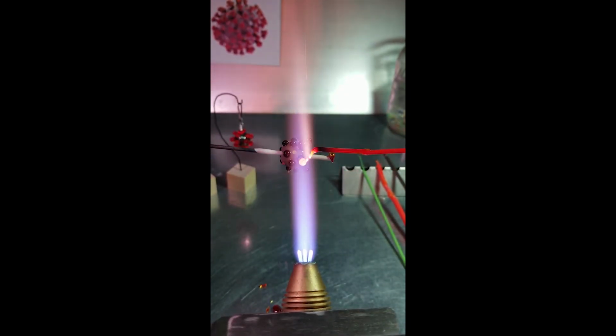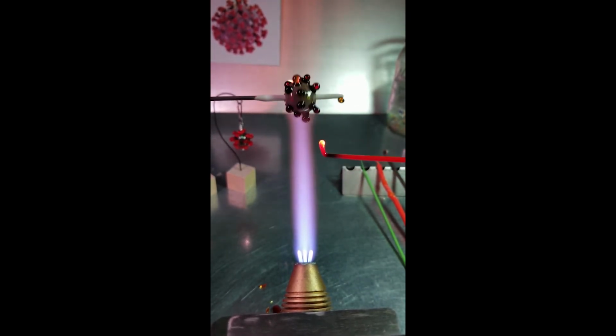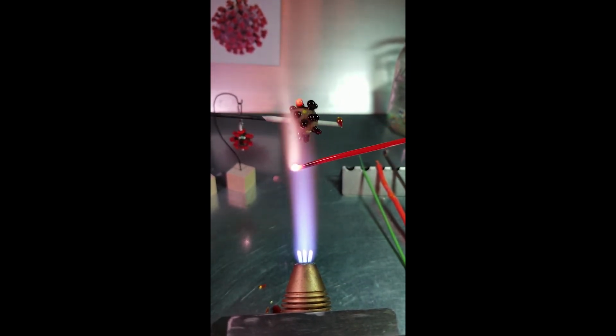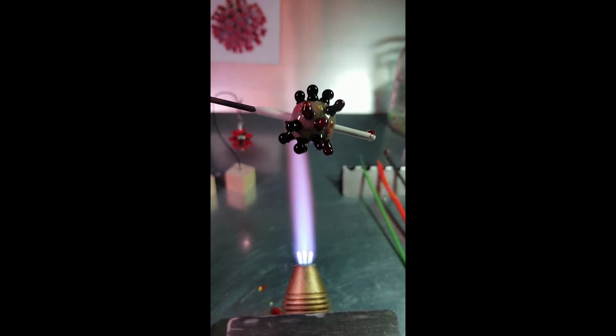Now I'm just going through, speeding it up again. I'm adding all of those balls on top, making sure they're all about the same size. I'm also keeping my base bead warm, because if I let the base bead cool down while I'm adding all these details, that can thermal shock and crack. So I do need to make sure I waft it through the flame and keep the base bead warm as well.